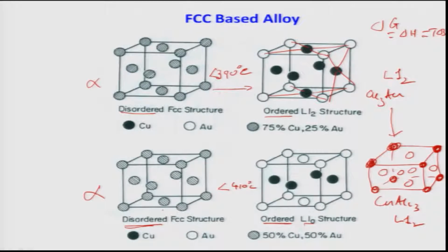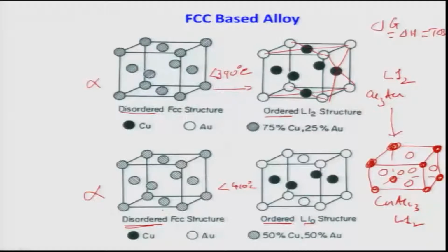We consider the 2 atoms in the face center positions in the unit cells, and if we draw a large number of unit cells, then we can connect them and get a face centered simple cubic structure that way. So this is nothing but 4 simple cubic sublattices, 1 gold type and 3 copper type. That can always be done for any structure.